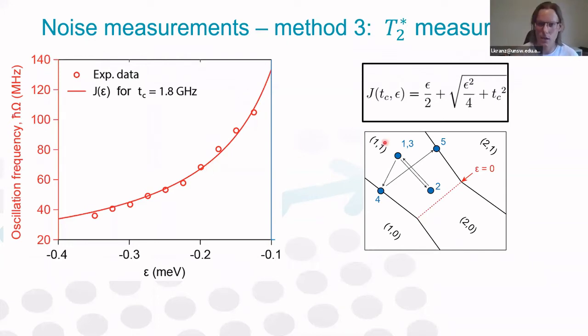And we fit this data with this equation here, which is derived from the Hubbard model. And you see the exchange interaction is not only dependent on detuning, but also on this parameter here, tC, which stands for tunnel coupling. And for now, we use the tunnel coupling as a fit function, and by fitting the data, we get a tunnel coupling of around 2 gigahertz for this device.